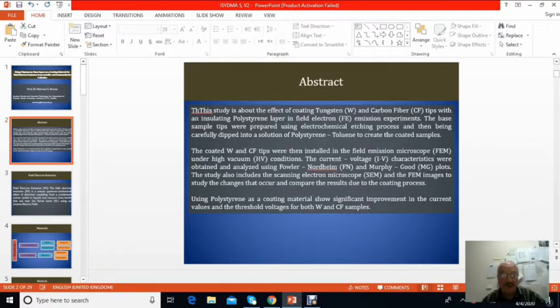The coating material consisted of a solution of polystyrene and toluene to create the composite sample. Then the clean tips were installed in the locally built field emission microscopes under high vacuum conditions and were tested in clean mode before coating, and then after coating, and comparisons were made between the two modes. Techniques were employed to use Fowler-Nordheim FN and Murphy-Good MG plots to characterize the results.